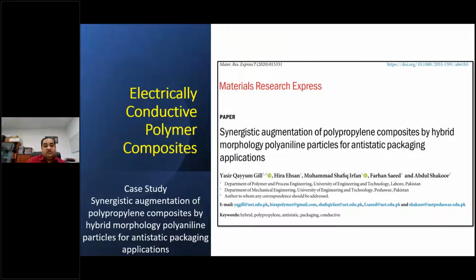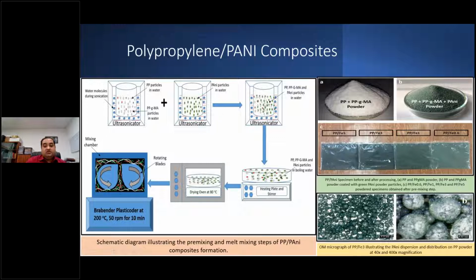In this area, once again, we utilized our developed polymer processing technique of ultrasonication, and based upon that, we were able to develop composites that showed very good characteristics. Now, in this slide, you can see the prepared powder, and along with the prepared powder, the polypropylene and polyaniline specimen before and after processing are shown to you over here, that they retain their green color, and the coating of the polyaniline on the surface of polypropylene is shown in this slide at the bottom, where the presence of green color ensured us uniform coating by the technique that we have developed.